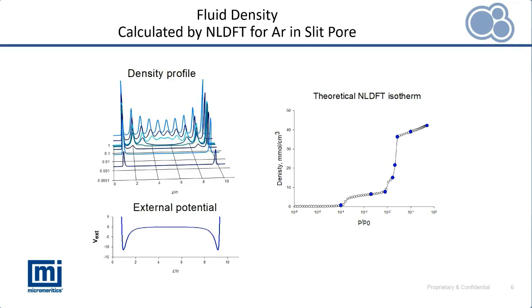Then there is a second peak, and in order to obtain condensation here, we should take into account the interaction between the molecules that are already adsorbed. So this condensation is due to interaction between adsorbed molecules, because the external potential does not allow for additional adsorption. So what is in the middle of this pore is due to interaction between adsorbed molecules.